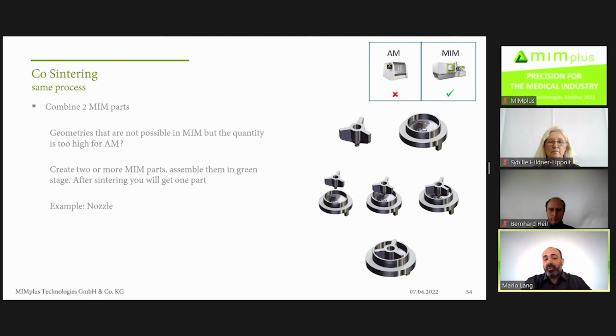Co-sintering, same process, combine 2 MIM parts. So the part you see on the right is a nozzle for an injection system and it's really in high volume. So it is a MIM part, because of the quantities. But on the other side, there are undercuts in the assembly. So this part cannot be realized technically in a tool.